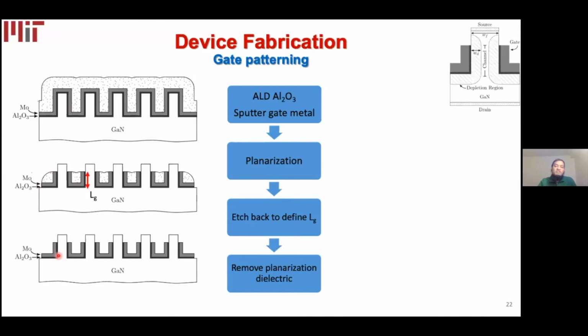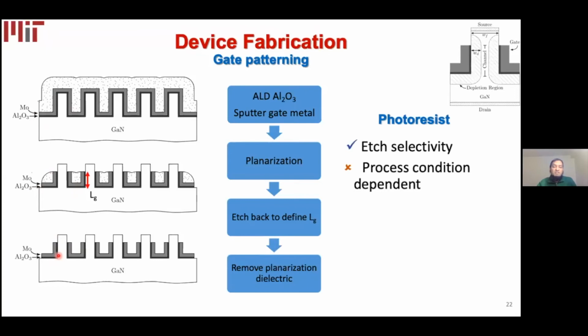So in the first generation of devices, we were using a photoresist-based planarization process. The advantage of this photoresist-based planarization is it's etch selective because we can just etch it with an oxygen plasma. However, since it's a photoresist spin-on, it also depends on the process parameters and it's really hard to control. So recently, we have developed a PECVD silicon dioxide-based planarization technology, which is very robust, and the etch chemistry is similar to our gate metal patterning chemistry. So we'll have to optimize the etch process to get the perfect gate patterning process.